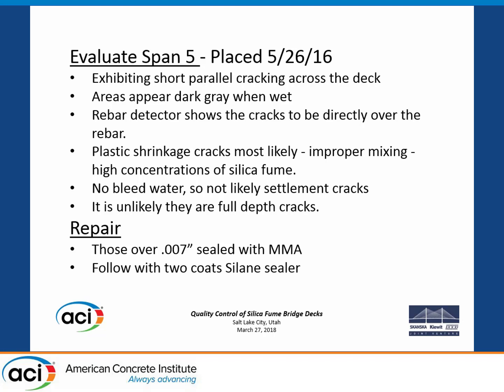Didn't we have an argument in our committee meeting about settlement cracks? Are they settlement cracks? Settlement cracks occur over rebar. But these can't be because there's no bleed water to promote settlement cracks. And it's unlikely they're full depth. They're over the rebar, that's where it popped. 7-inch, 7/1000, seal them, follow with 2 coats of silane.